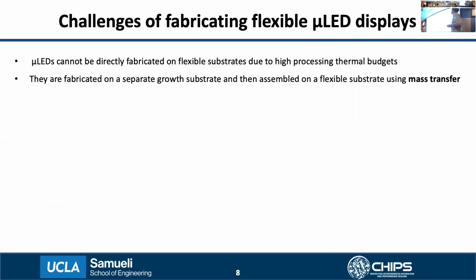However, there are several challenges for fabricating these flexible micro LED displays. So micro LEDs, as I mentioned earlier, are based on inorganic 3-5 semiconductors like gallium nitride, indium phosphide, that cannot be directly fabricated on flexible organic substrates because of their high processing temperatures as well as lattice matching considerations. So the way they are usually integrated on the flexible substrate is to first fabricate them on a separate growth substrate, and then detach them from this growth substrate and then massively parallelly pick them up and assemble them onto a target flexible substrate using a process called mass transfer, which I'll discuss more in detail in the coming slides.